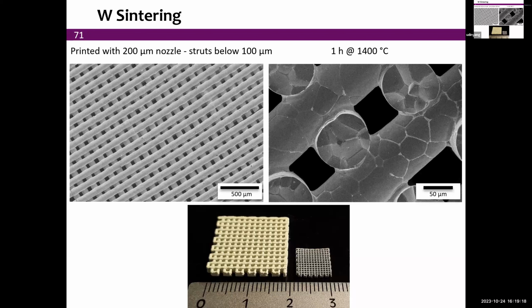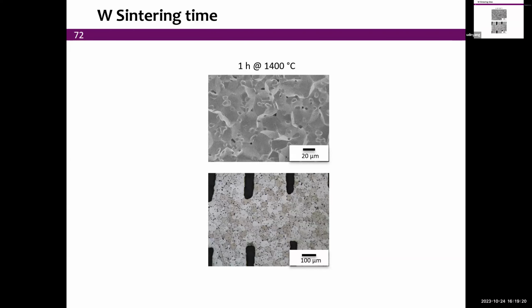Here we are. So now we played a bit with the sintering time. This is a fracture surface. This is a cross-section surface. I want you to look at the size of the grains, but you can see both in cross-sections and in the fracture fractography. So this was 1 hour at 1400 degrees C.